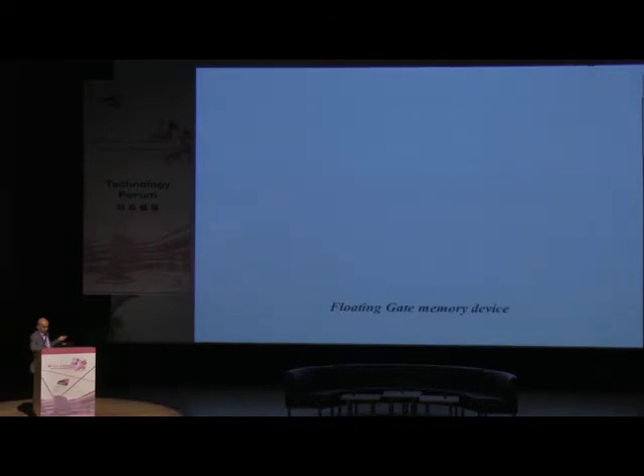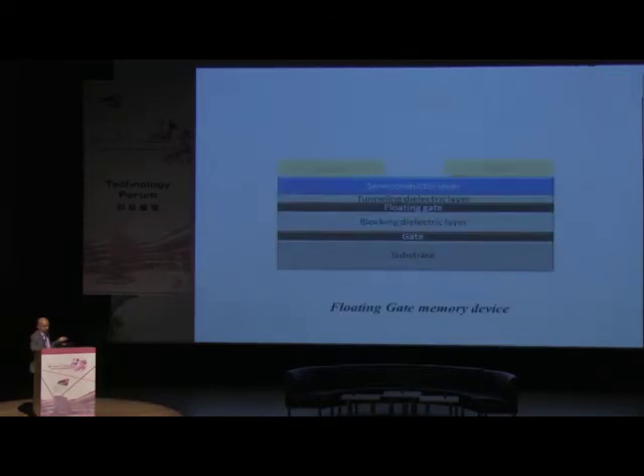Now, all these devices I'm talking about have a single layer. In the device structure, you are storing all this data next to the dielectric layer, which is called the floating gate. Now, if you don't have a layer, all these charges that come from the semiconductor layer can get back to the semiconductor layer. So we put another layer called the tunneling dielectric layer, which is just 10 nanometers. By doing so, the charges cannot easily get back, and you can enhance retention time. That is how long you can store the data inside the device.